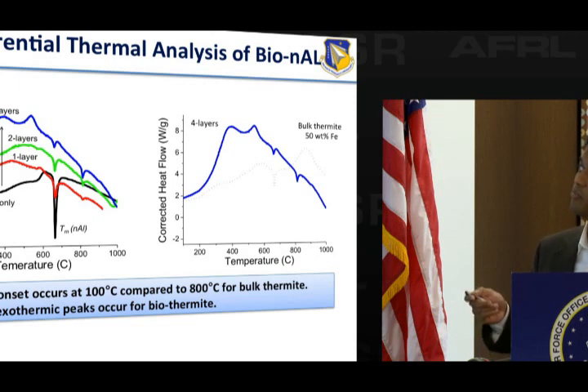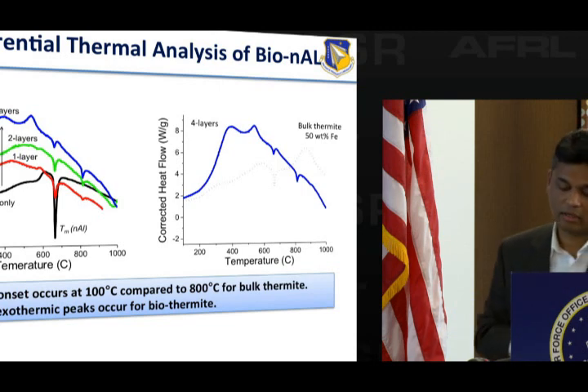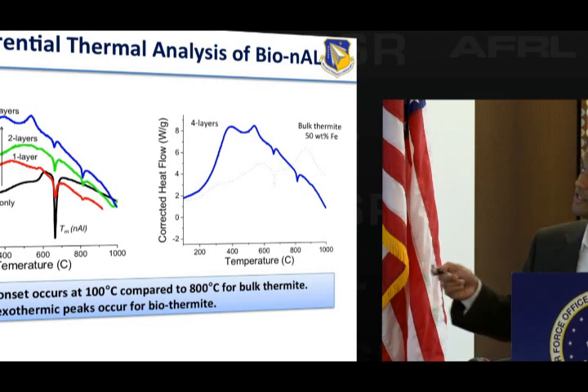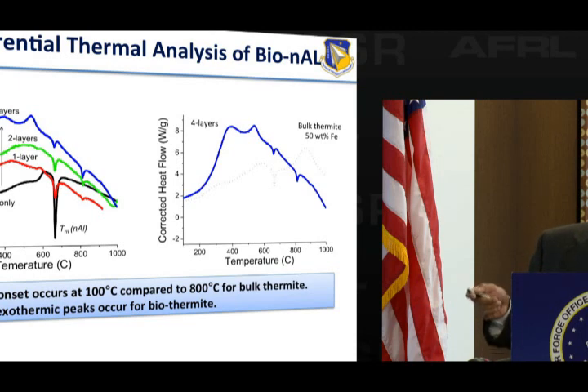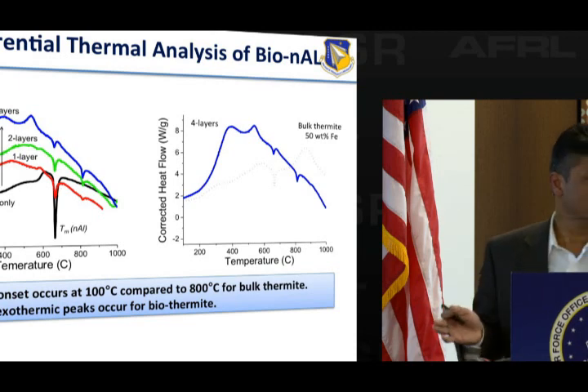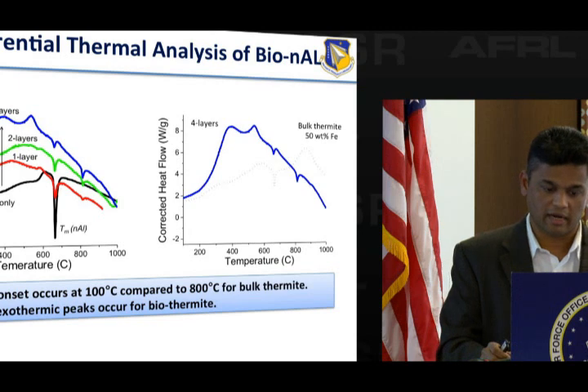This is combining just bulk thermite. This is 50% by weight iron oxide with nanoaluminum. You can see this is the reaction kinetics, and this is our four-layer ferritin-based kinetics. You can see a huge difference in the reaction kinetics.